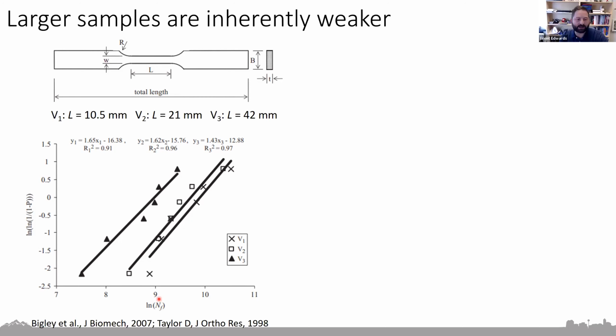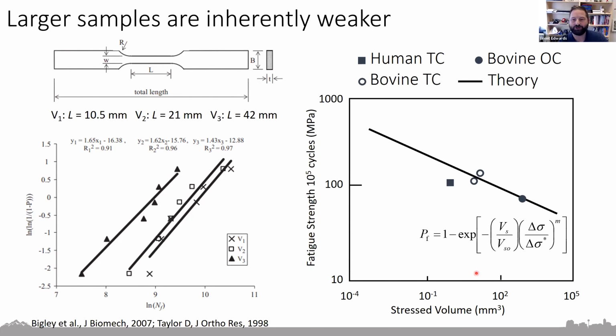it fits another kind of distribution called the Weibull distribution. The cumulative probability distribution for the Weibull distribution is this here. I'm not going to go into detail, but all you have to know is that this is a distribution used almost all the time in engineering to determine the probability of failure of a material under cyclic loading. And so what David Taylor did in